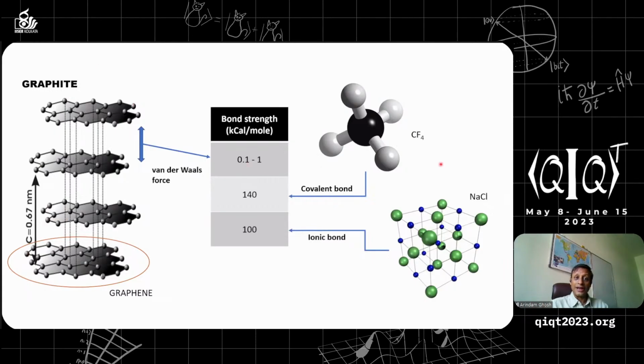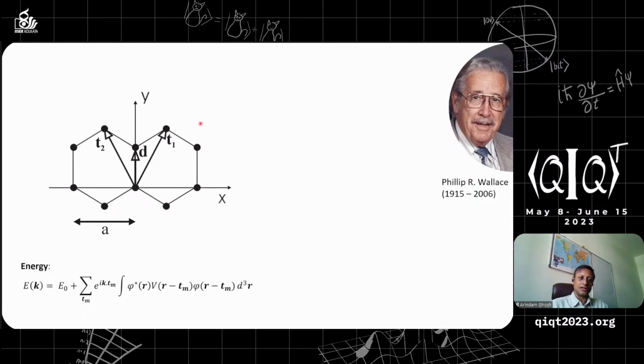Compared to, say, covalent bonds or an ionic bond such as in carbon tetrafluoride or sodium chloride, these are much weaker, about 1,000 times weaker. As a result, you can make these materials in a single layer. And just to give you a snapshot of graphene, I told you why these unique band structures can be developed. 2D material is one of the members of the topological or quantum materials that I talked about. Because of the unique crystal structure, the electron energy as a function of momentum becomes very different from standard